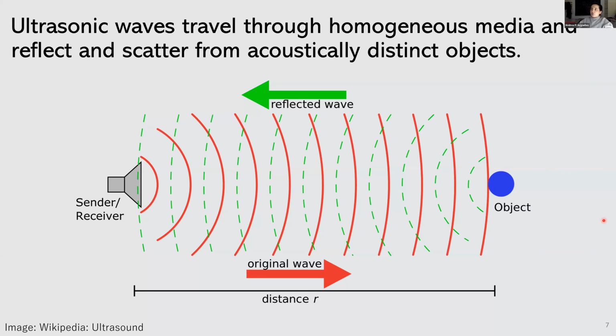So how do we actually use ultrasound to understand this? So in the, again, conventional NDE sense, we're dealing with the direct reflection of ultrasonic waves by an object in the material. So we're dealing with diffraction limited imaging, where you essentially need flaws that are at least half that wavelength in order to get a reflection from the flaw, which is fine. We do use some of that information for some of the parts, because even though the process should be optimized to not obtain flaws that are that large, the reality is that sometimes in the responses that we're getting, we're seeing that that is still happening.